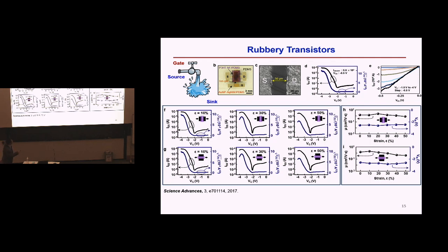By applying voltage. From this curve here, you can see the black curve represents the transfer curve that utilizes VG. Then by applying 1 or 2 volts, you can modulate the source and drain current by a few orders of magnitude. And more importantly, this device you can stretch along different directions. This is the channel length direction, and you can stretch about 50%.